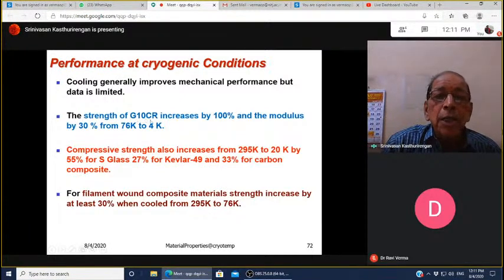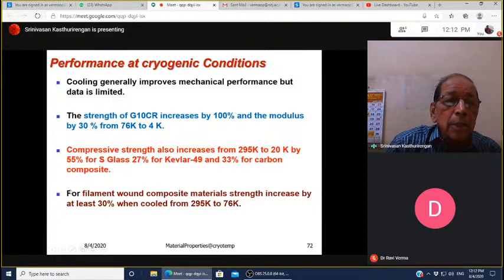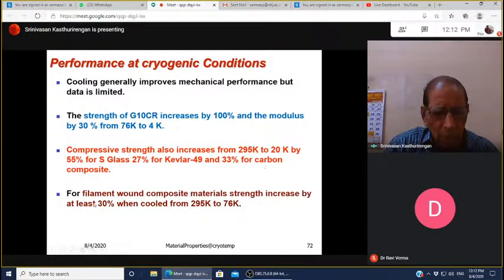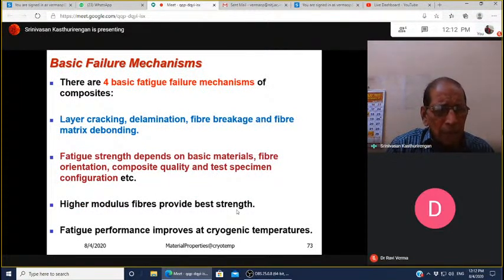The strength of G10CR increases by 100% and the modulus by 30% when you cool from 76 Kelvin to 4 Kelvin. The compressive strength also increases in the range from 295 to 20K for different glasses, for example, 55% for S-glass, 27% for Kevlar 49, and 33% for carbon composites. The filament wound composite material strength increases at least by 30% when cooled from 295 Kelvin to 76. So what it shows is that when you operate at low temperature, the strength and the mechanical performance of these composites improves. Okay, what are the failure mechanisms?